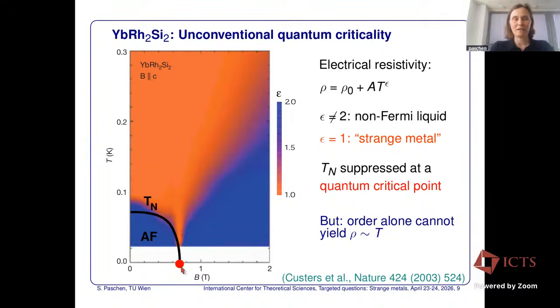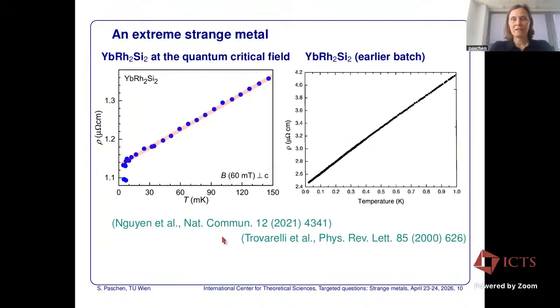So it is a quantum critical point, yes, but it is not. The strange metal fluctuations, as we believe and realize more and more, are not only created by the presence of this order parameter. For instance, the theoretical description of the order parameter criticality cannot, in a clean system, give rise to linear in temperature resistivity. So we think that the order is more a consequence of this critical point here than the driving force for everything. Just to show you that color-coded data have real meaning.